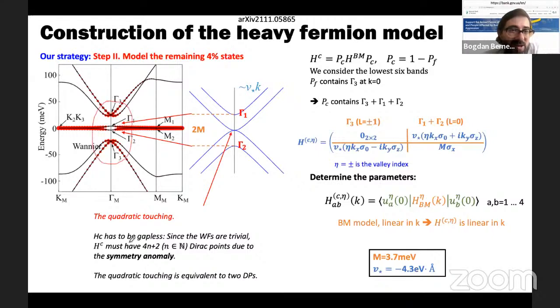At the gamma point, we know that the f-electrons, the localized states, have the wrong representation. They have a gamma 3 representation, whereas the flat bands of the Bistritzer-MacDonald model have gamma 1, gamma 2. But we took these 6 bands together per valley per spin, and we use 1 gamma 3, the 2-dimensional representation, to obtain the localized electrons. So now we're left over with the other gamma 3, for example, and gamma 1, gamma 2. So the conduction electrons, or the itinerant electrons, have to form a 4x4 Hamiltonian. This is a 2-dimensional, this 1-dimensional, they form a 4x4 Hamiltonian. And the Hamiltonian, from symmetry reasons, has to look like this.